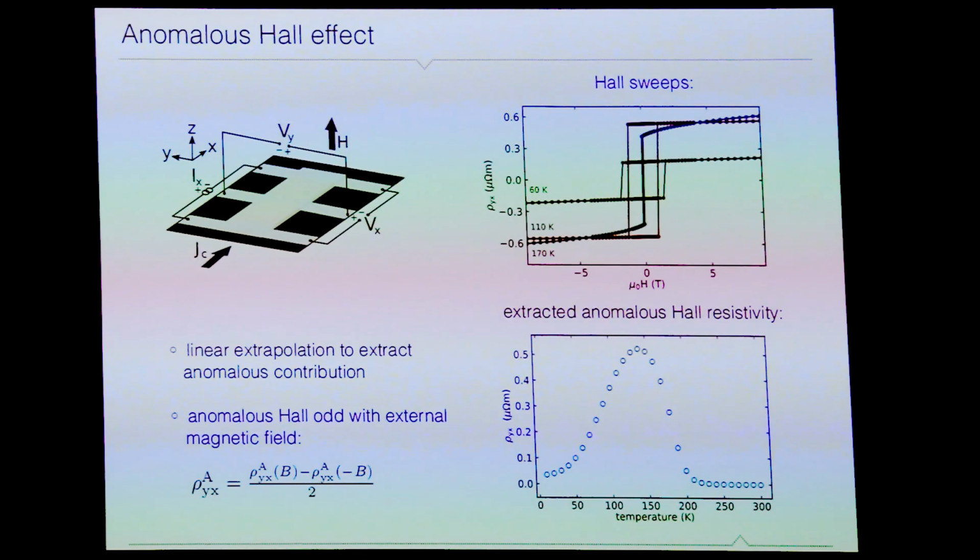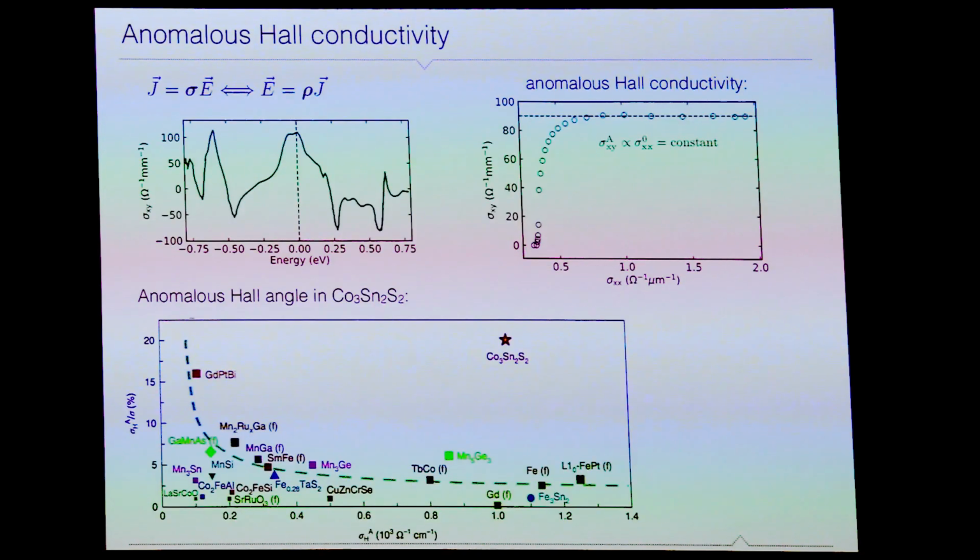In the previous talk, it was already mentioned that when theoreticians calculate anything for the anomalous Hall, it is always conductivity. So theoreticians talk in conductivity, and experimentalists talk in resistivity, because resistivity is way easier to measure. And if you directly want to measure conductivity, this is very complicated. So what you have to do is, that is actually how you would write it down.